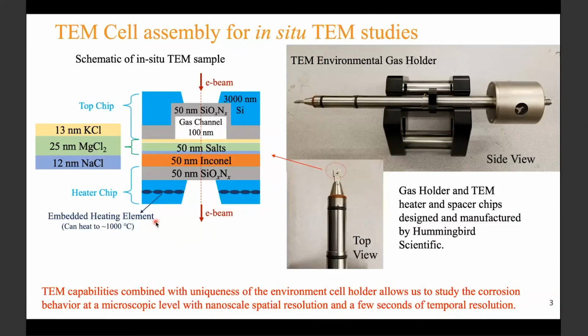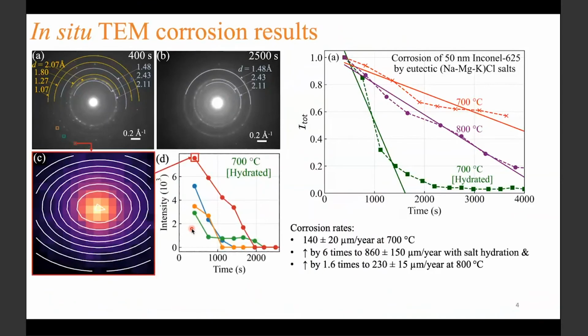in a controlled gas atmosphere. Such a unique environmental cell setting inside an ultra high vacuum microscope enabled me to study the corrosion behavior at a very microscopic level, with nanoscale spatial resolution and a few seconds of temporal resolution in real time. Moving forward, this slide presents some of the results of the high temperature corrosion experiments that I performed inside this high resolution microscope, which is the TEM.